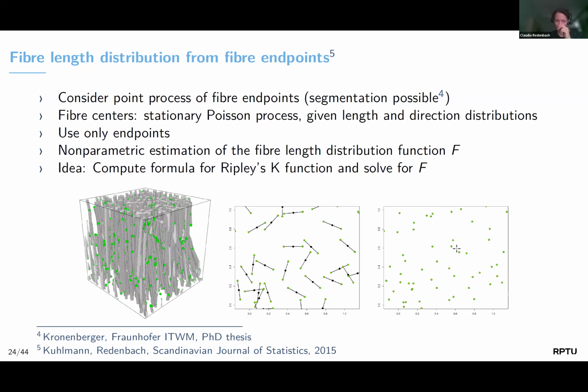How is that done? There is a classical spatial statistics summary statistic called Ripley's K function. And for such a process where you have a stationary Poisson process for initial points and then clusters, here the clusters being the two fiber endpoints given by some fixed distribution and being drawn IID, then this Ripley's K function can be computed explicitly, and it does depend on the fiber length distribution F. And it's very well known how to estimate K, and then you just have to solve the formula that you get for the F.